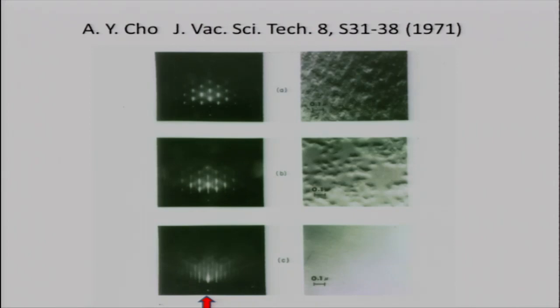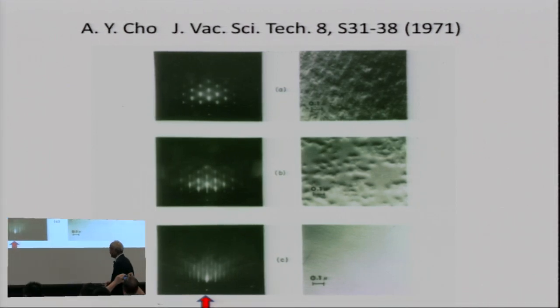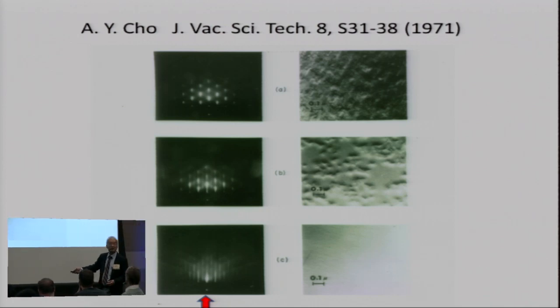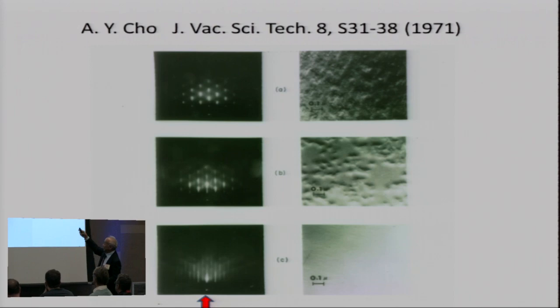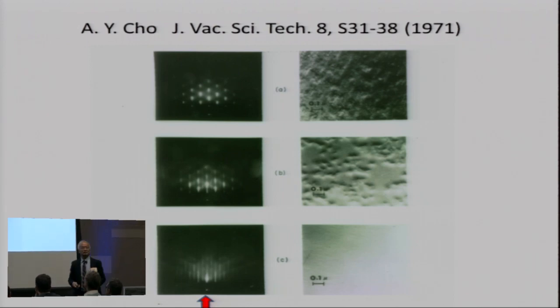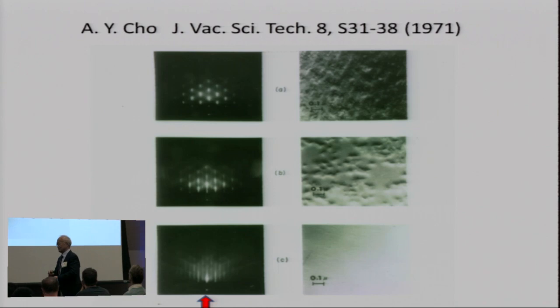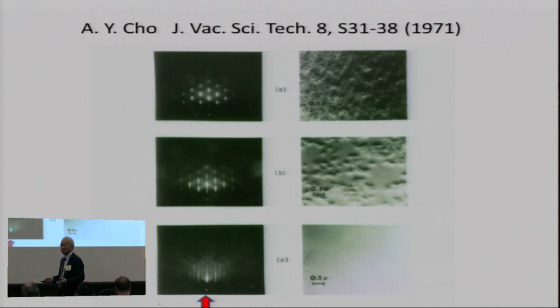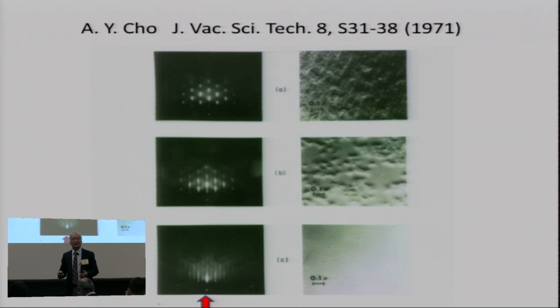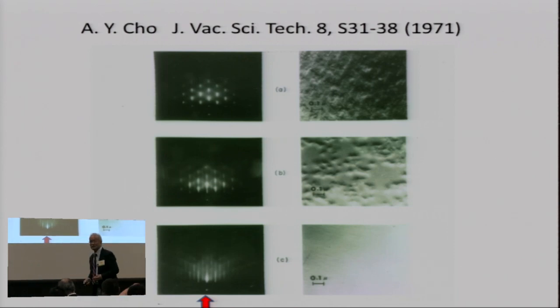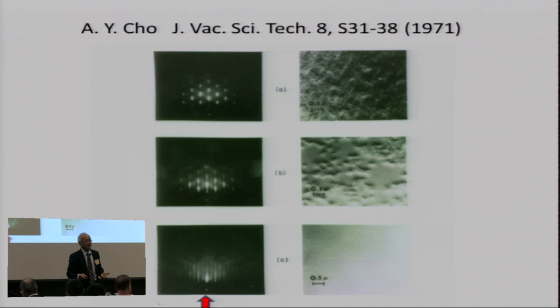Now, in the same year, 1971, I also reported the diffraction pattern on the left-hand side, and then the corresponding surface structure. Look at the carbon replica on the right-hand side. When you have a gallium arsenide surface, when you clean it with bromine methanol and think it's very clean, you put it in the MBE system, heat it up, dissolve the oxide, what happened? You look at the diffraction patterns: spotty diffractions. The reason is that after you heat it up, it has microfaceting. The surface has little tiny hills and valleys.